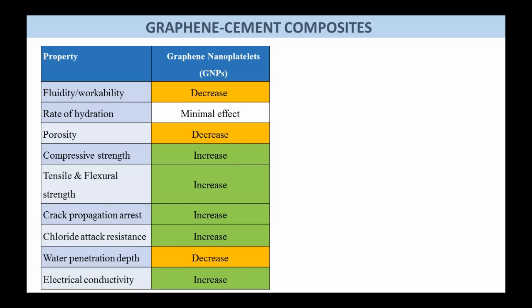And there is some general agreement in the literature as to what is the effect of graphene nanoplatelets when they're added in cement mortar or cement paste. And in general, the fluidity of the mix decreases dramatically. I think all authors agree on that, because graphene is a nanomaterial and it is very difficult to mix. And also we have seen improvements in strength and then a consequent improvement very often in the durability parameters as well.